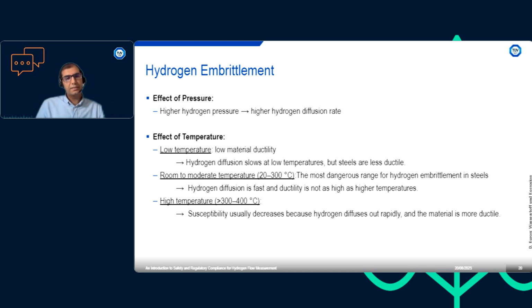For temperature, it is not as straightforward as that. At very low temperatures, materials have low ductility, so that increases the risk of embrittlement. But at the same time, because the temperature is low, hydrogen diffusion slows down as well. So that somehow balances the reduction in ductility.